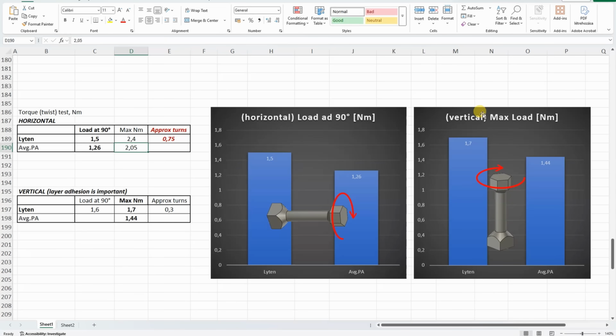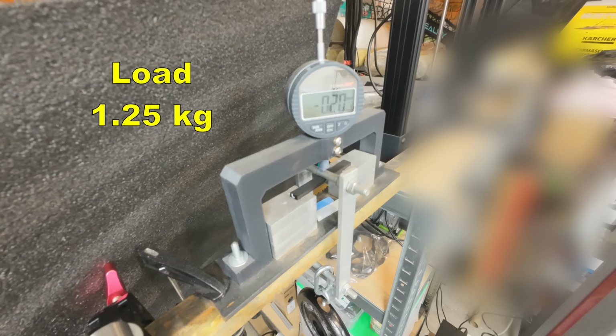In both cases, printed horizontally, usually I record the load in 90 degree rotation, it was stronger compared to the average PA. And printed vertically, usually I record here the maximal load, because in most cases I cannot do 90 degree rotation, but this material was an exception, and even here the maximal load was bigger compared to the average fiber reinforced nylon.